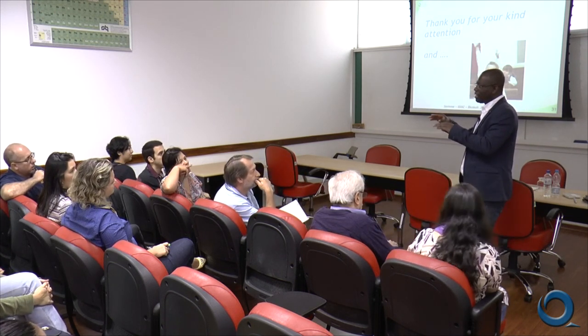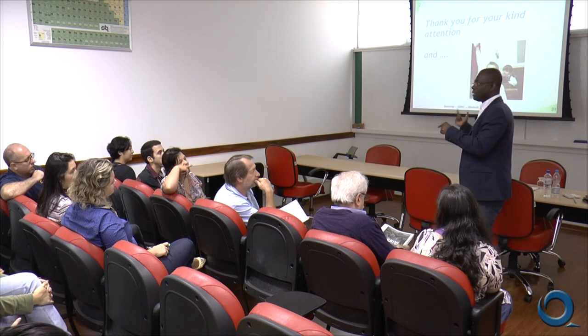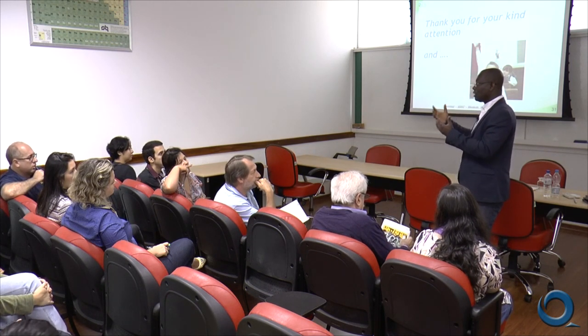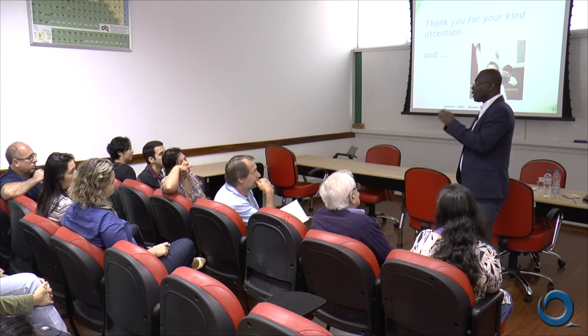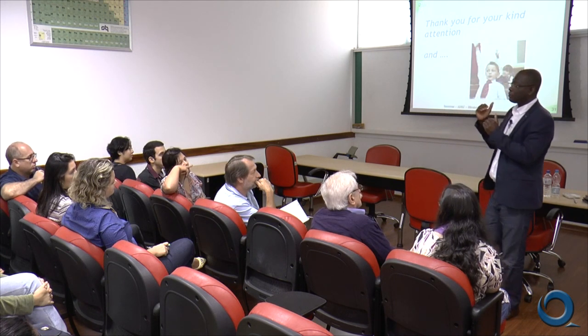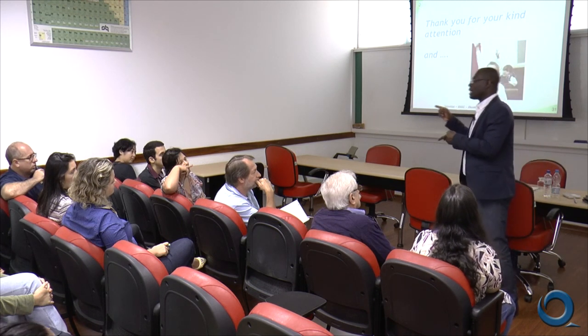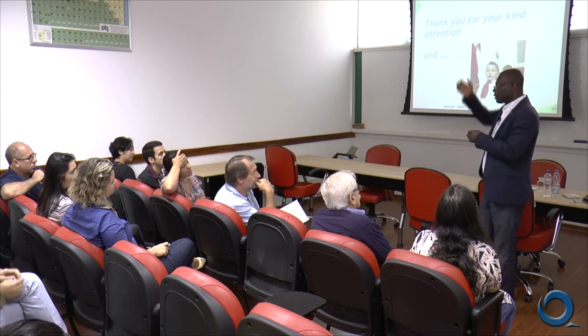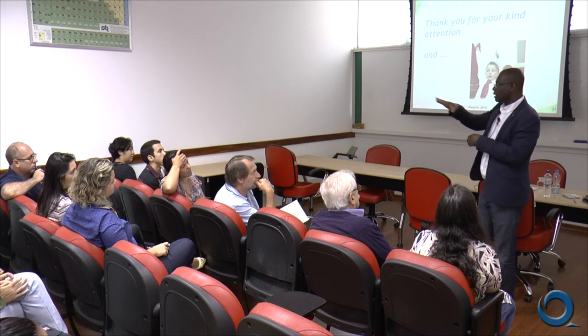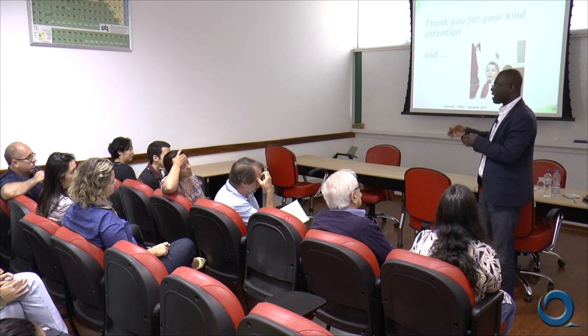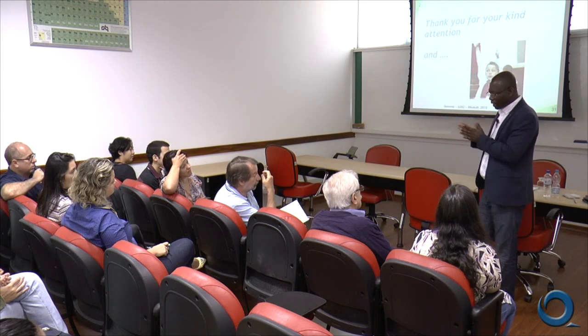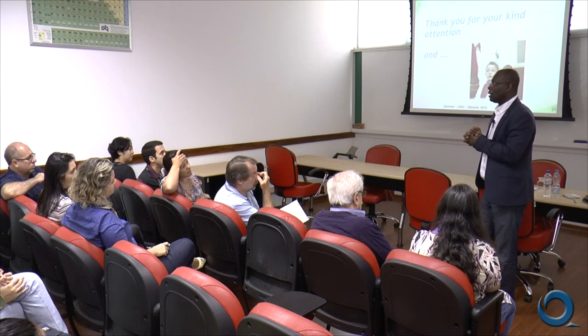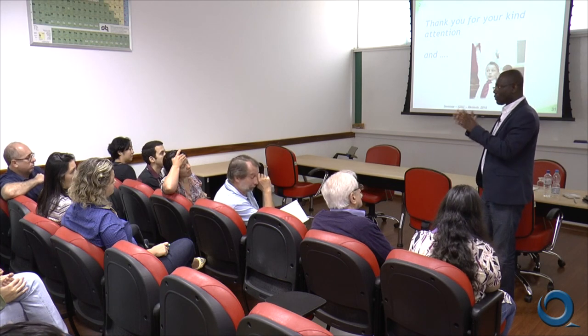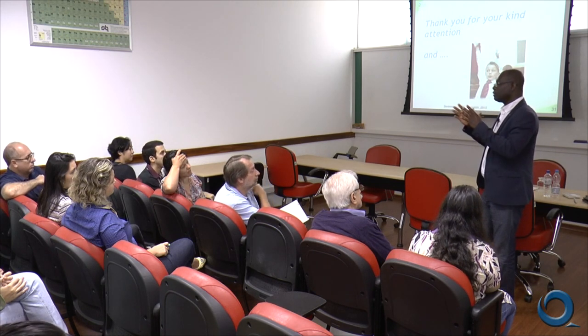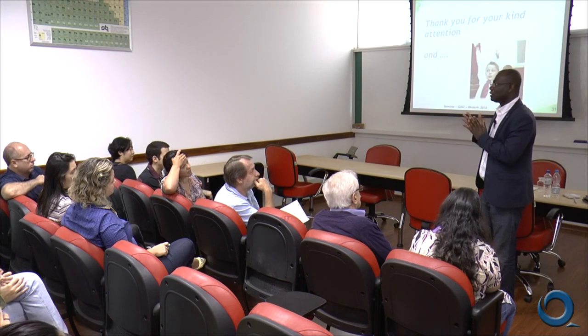This is very difficult. By XRD, we have no evidence of the presence of nickel. In HRTEM, we have some, because we can do EDX in the environment to see the percentage of nickel. This is our solution. But with XRD, we have no evidence of nickel. Yes.